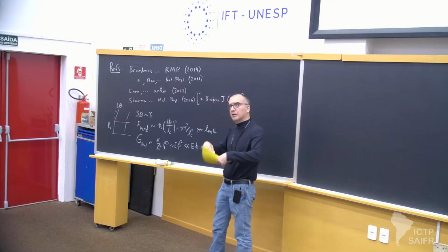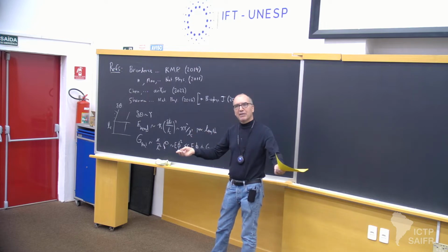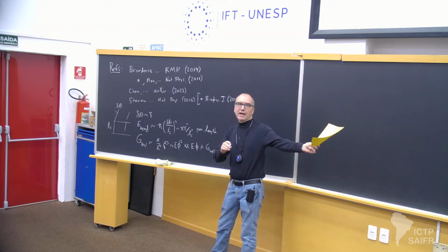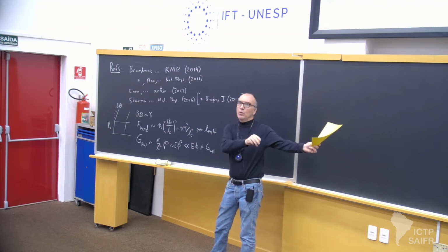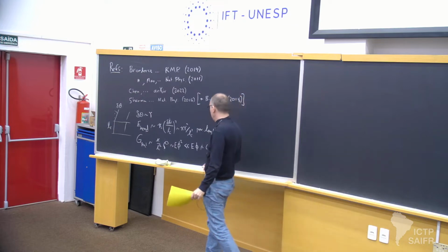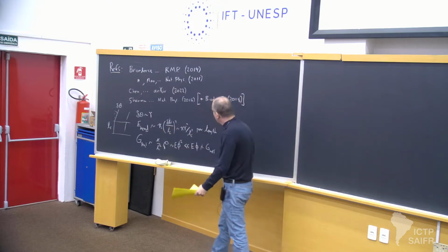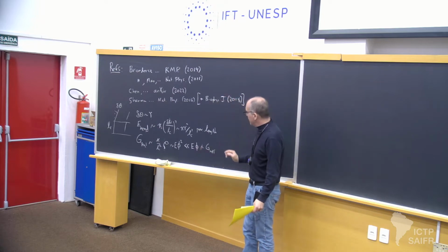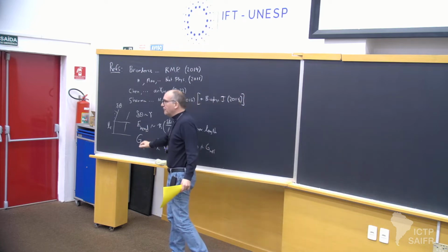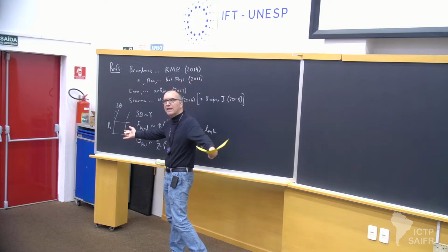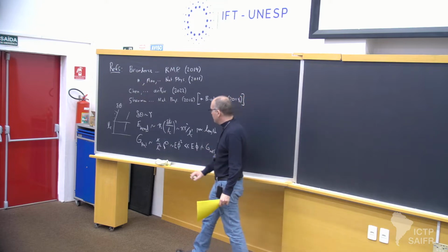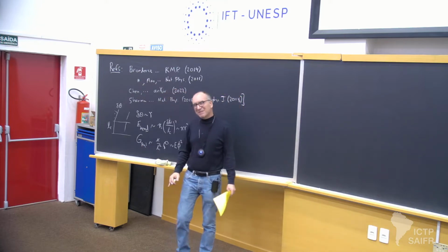At low volume fraction, I should have emphasized maybe last time, I think I did, but maybe I should re-emphasize: all those experiments I was talking about are typically at volume fractions of 1%, or usually even well below that. 0.1% would be typical. Milligram per milliliter is the standard range. Okay, so anyway, this certainly suggests that since this is a softer mode of deformation, this should win, right? If you deform a system, it'll look for the easy way out, right? And so it certainly suggests that affine never happens, bend always dominates, but it's not so simple,